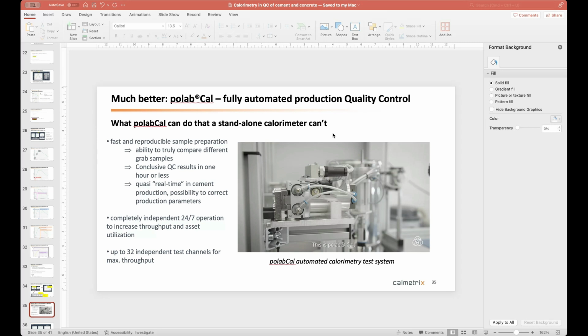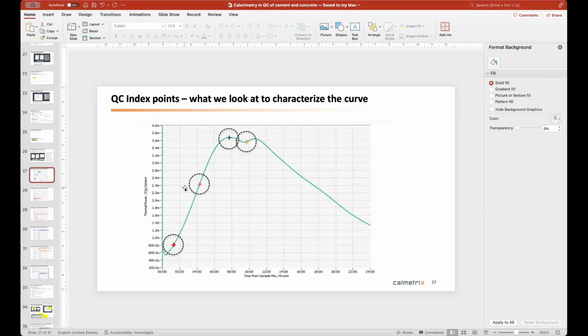Does isothermal calorimetry pick up the influence of aluminates from slag on the sulfate depletion peak in blended cements? Oh, very much so. It's extremely visual. A good looking cement, like the one we have here, has its sulfate depletion peak a few hours after the main peak. If you put in a slag with high aluminate content that consumes all of the sulfates, this peak will move to the left.